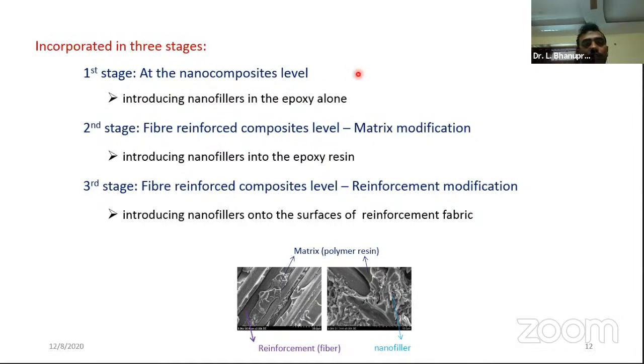From this beginning work at the nanocomposite level, I received some challenging results, and with that I went ahead and modified the fiber-reinforced composite system. First I tried introducing nanofillers in the matrix system. Then I introduced nanofillers onto the surfaces of the reinforcement fabric. Here I used direct dispersion methods for the matrix, and in the reinforcement modification system, I used electrophoretic deposition, as the figures or microscopic images illustrate here. So nanofillers are being considered in the matrix system.